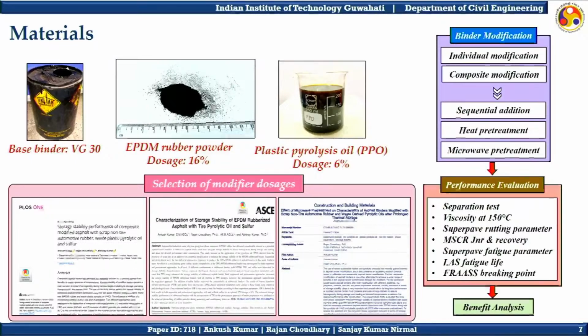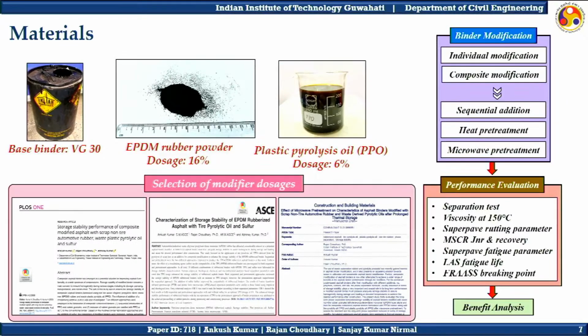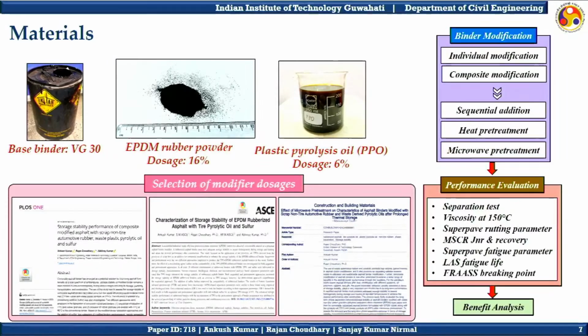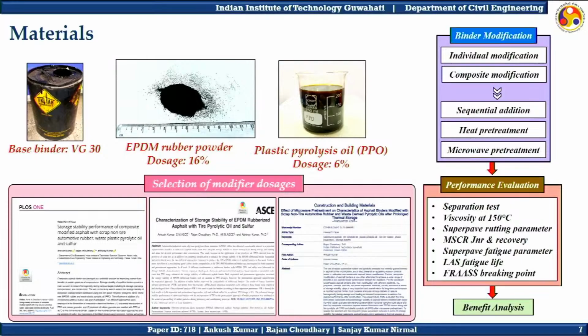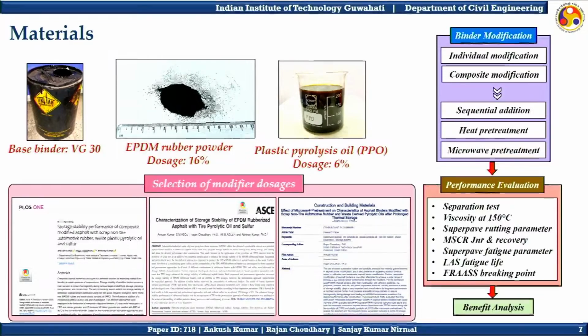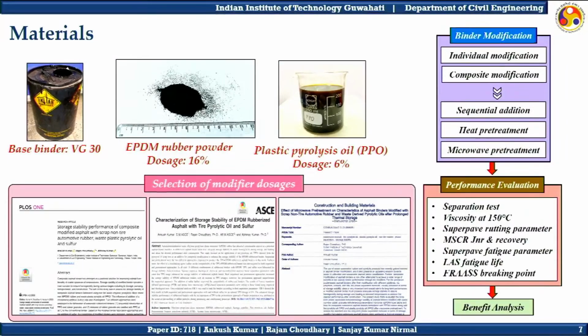Moving forward, for binder modification, two different modification approaches were used. The first one was the individual modification, where respective doses of individual modifiers were used. And in composite modification, three different methods were used: sequential addition, heat pretreatment, and microwave pretreatment, which we will discuss in detail in the coming slides. The prepared binders were evaluated in terms of separation test, viscosity at 150 degrees Celsius, and rutting characterization in terms of Superpave rutting parameter and MSCR test, fatigue characterization in terms of Superpave fatigue parameter and LAS, and low temperature characterization in terms of Fraass breaking point.